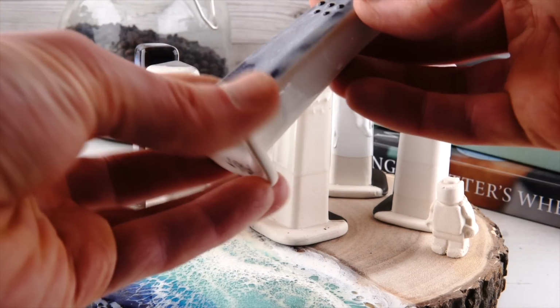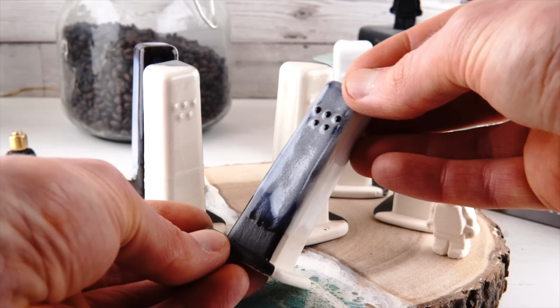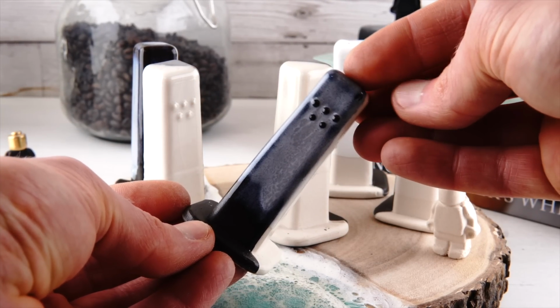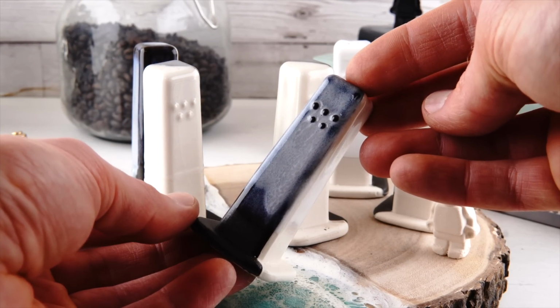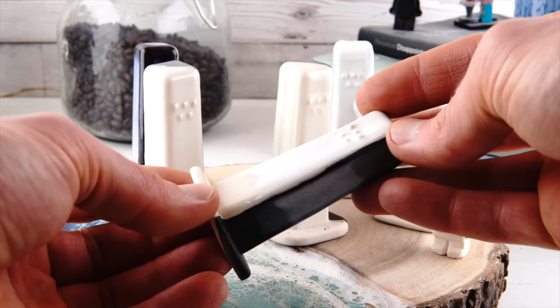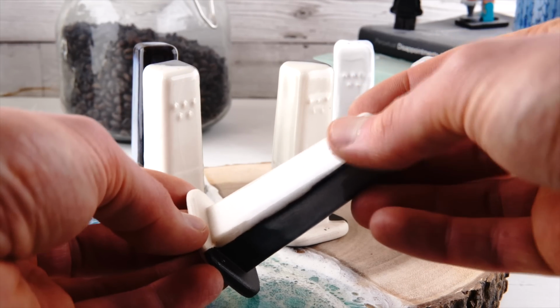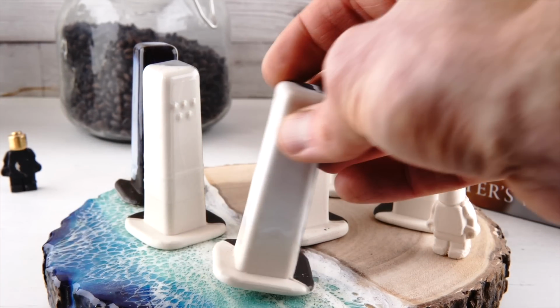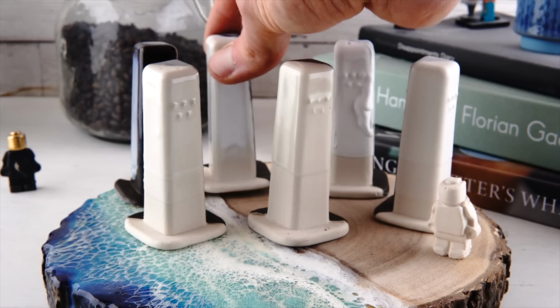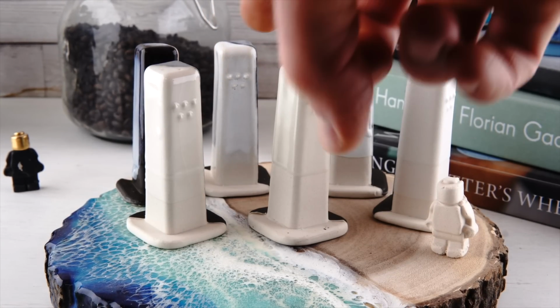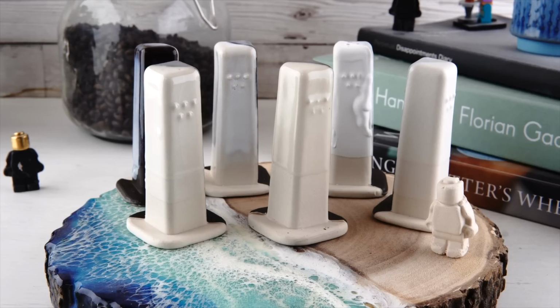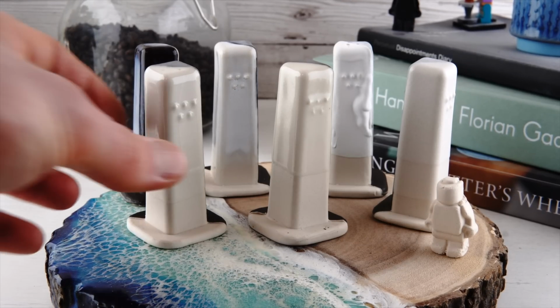This one actually, it's done something kind of cool on that side, but this was the other really high frit recipe, and again, as you can see there, blistered because there's too much boron. Completely overfired for this temperature. That recipe could be fired about 200 degrees colder and would still melt. Completely inappropriate for what we requested.